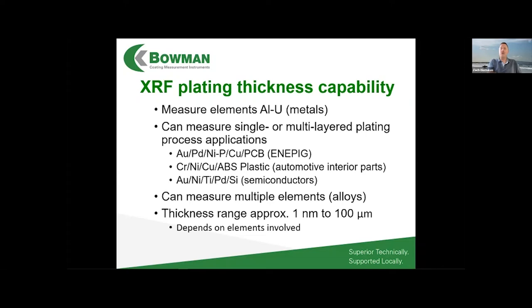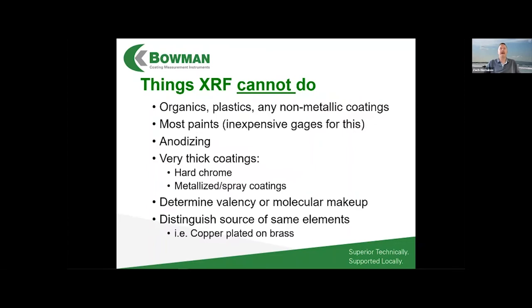A zinc nickel on steel coating is one we run into a lot. So we can measure both the thickness and the composition of an application like that. So that's something we can do simultaneously. And then I get the question a lot, what thickness range can you measure? I'll get a bit more into that, but we're typically talking in the level of micron, submicron levels, around 1 nanometer up to around 100 microns of thickness, but it really depends on the elements involved. So again, I'll get more into that.